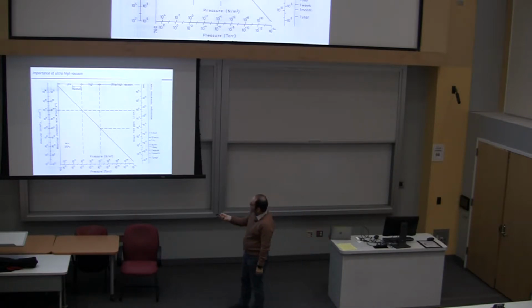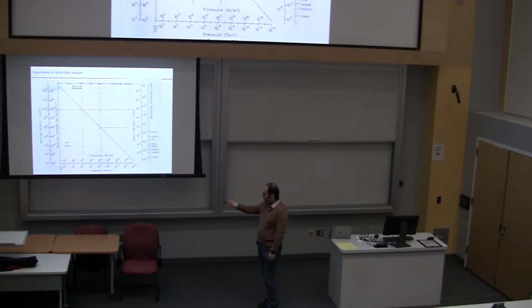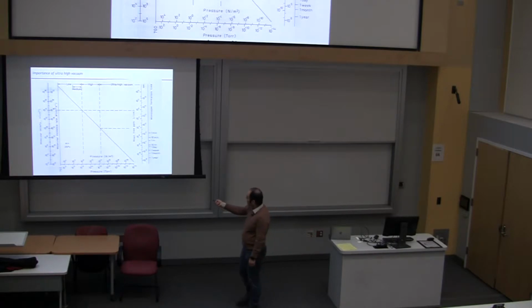So this graph actually is a very nice graph, I think, for showing why ultra high vacuum is important. The x-axis is the pressure, so that side is high pressure, the right-hand side is very low pressure. And on this axis, let's just focus on the monolayer formation time. If you are at high pressure, that means you have other things. Let's say for now it's just oxygen and we are just thinking about the oxidation of the surface. If your pressure is, let's say, 1 torr, you need about a microsecond to form a monolayer, the first bonding of oxygen to a material, right?